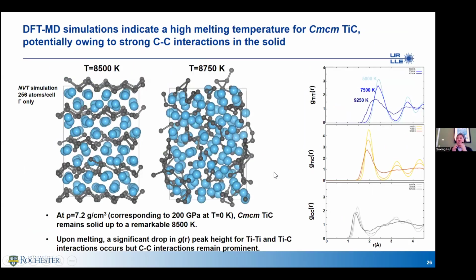So of course, when you need diamond formation, one of the natural thoughts is that you need to melt the system first, right? Because if you don't melt the system, they will lock in space. The naive idea is once you melt the system, the titanium atoms might move away, they will become fluid, and make space for the carbon to find the other carbons, right? So the first thing is to make this system melt and see what could happen. So what Katie did is to use this so-called heating until it melts method, right?